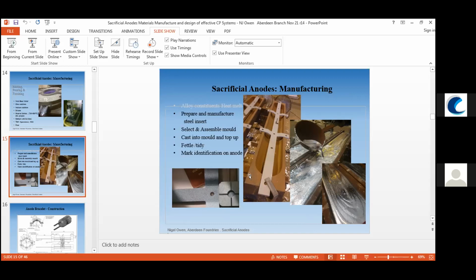It sort of sits on the surface and keys into the blasted surface. Zinc is a different animal there. When galvanizing, it does actually coat and form an intermetallic bond. So if you've got your insert in place, you can then pour your metal basically over the top of it, and leave the straps sticking out the sides.